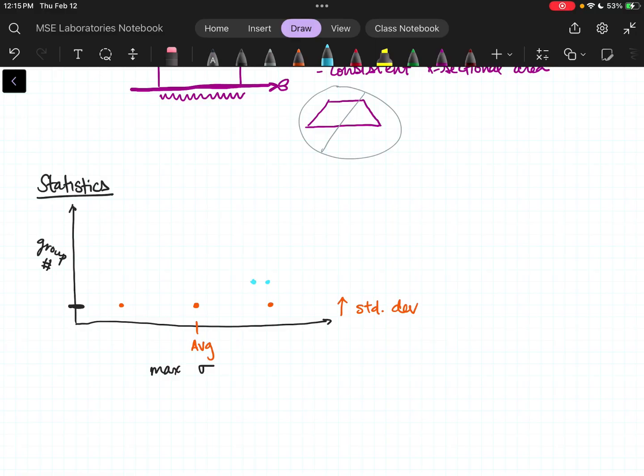Now let's say instead I test 5 specimens, and I find that this is more like my distribution here. So I'm getting more specimens that were strong. Still some that were really weak, still some that were a little bit weak, but I'm getting more of these strong specimens. In this case, my average is here, and I have a standard deviation.